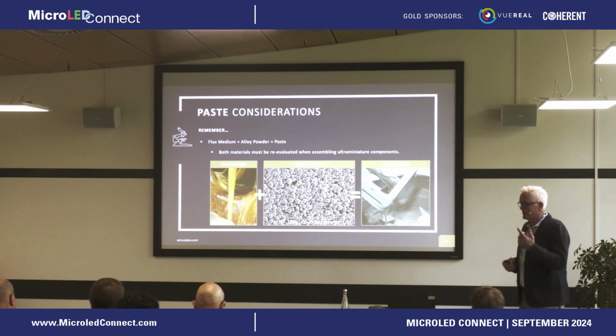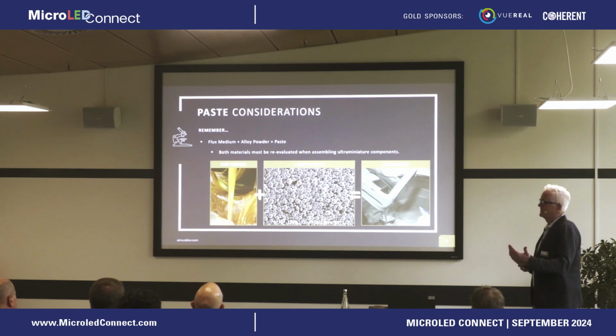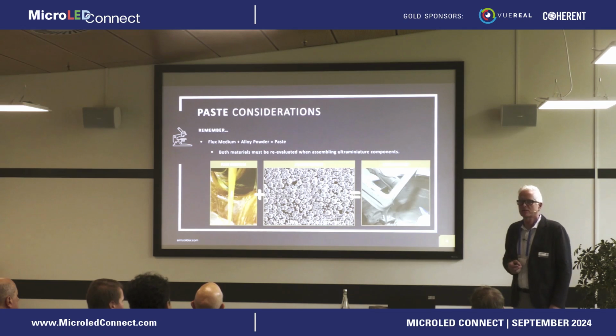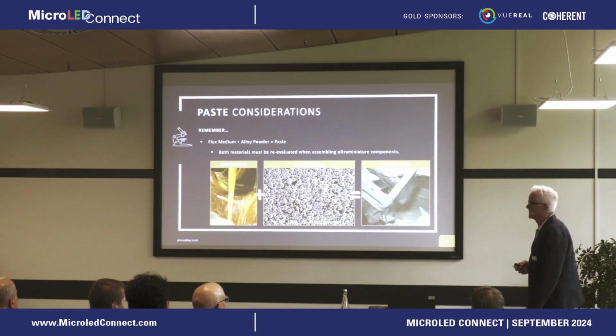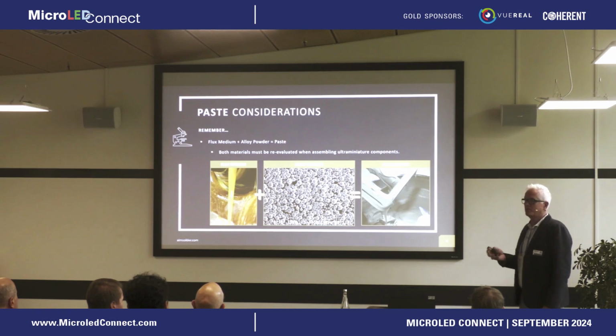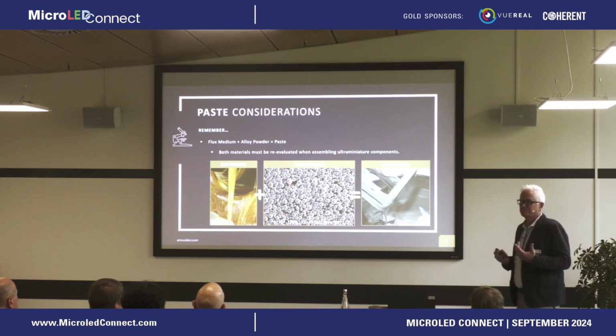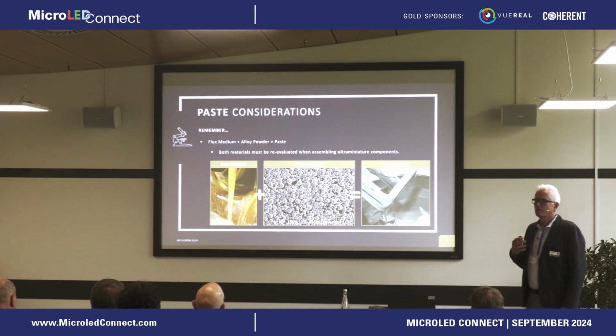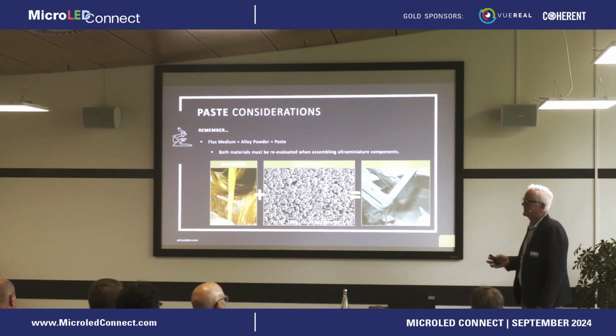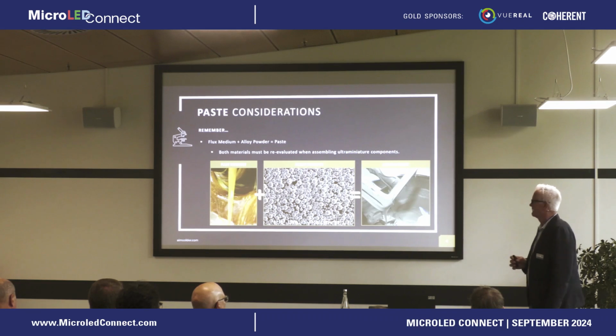So we use solder paste. Solder paste has been around, I've been in this business since 1994, and that's about when surface mount started to gain a lot of traction as a commoditized process. It's flux medium. I'll refer to medium a lot of times. It's the term we use internally. It's goo, like wheel bearing grease. And alloy powder. And alloy powder is 90% of the material by weight, so it's mostly alloy powder. It's about 50-50 ratio by volume.